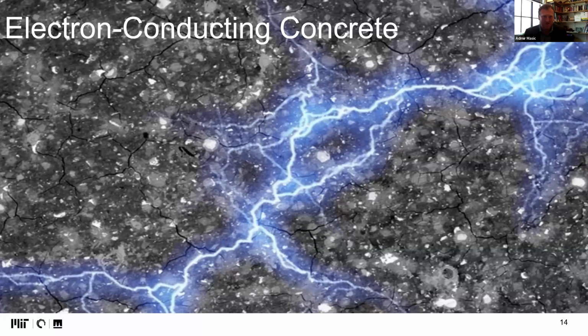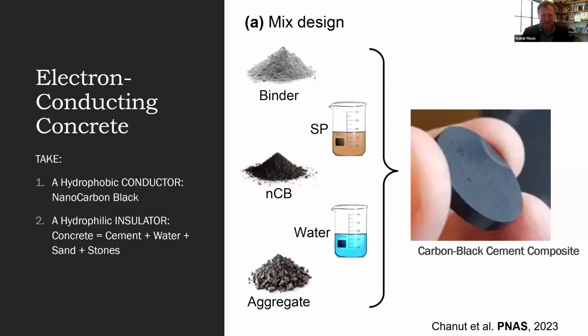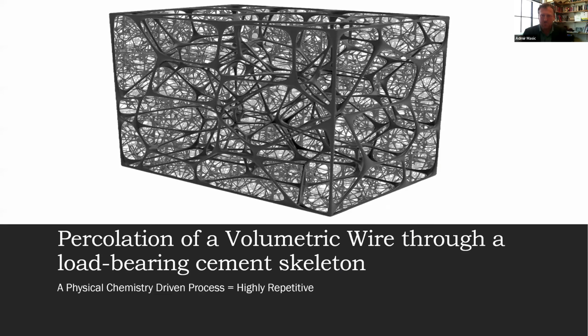But let me now talk about electron-conducting concrete that really makes us very excited in the lab. Here we are talking about making concrete, that is an insulator, into a conductive material, meaning that we introduce some sort of conductive material, and we focus on nanocarbon black that is mixed with the cement and some admixtures and water, and of course aggregate for concrete, and then turns into a carbon black cement composite that conducts electricity. The mechanism behind this is nanotechnology, where these nanocarbon black particles self-assemble during the hydration process into percolated volumetric wire. That is a physical chemistry-driven process and therefore highly repeatable.